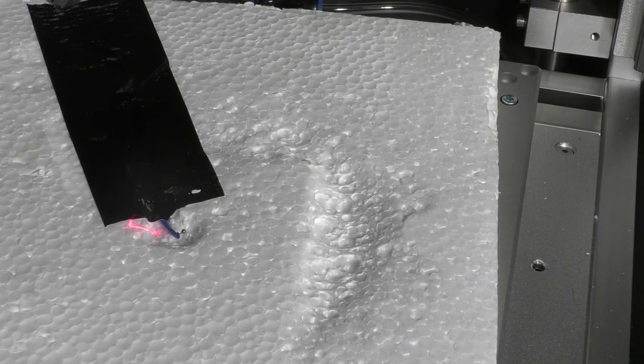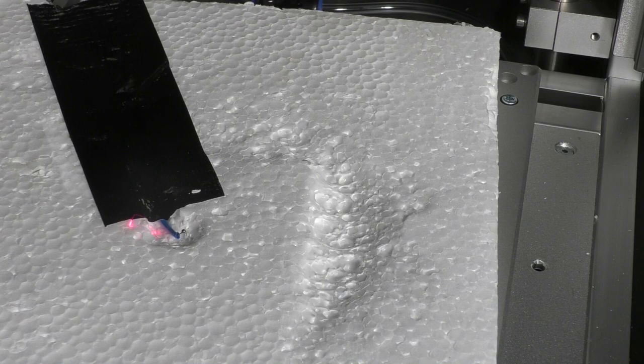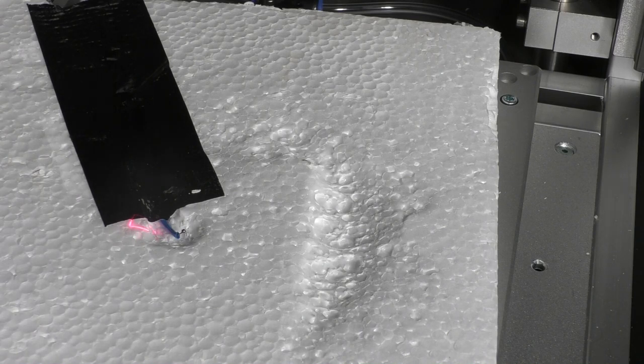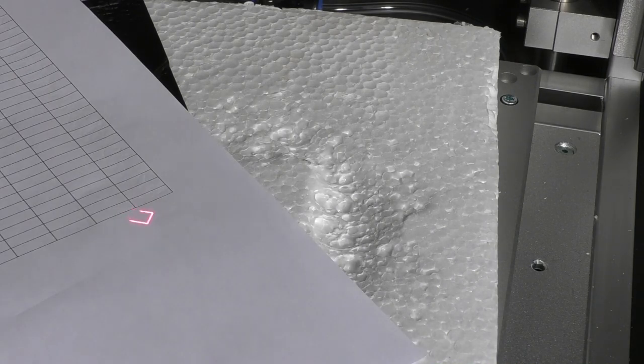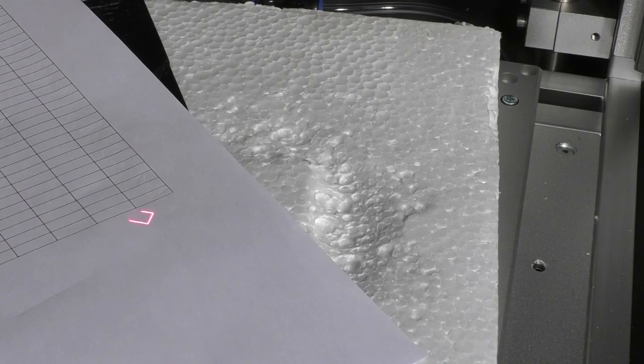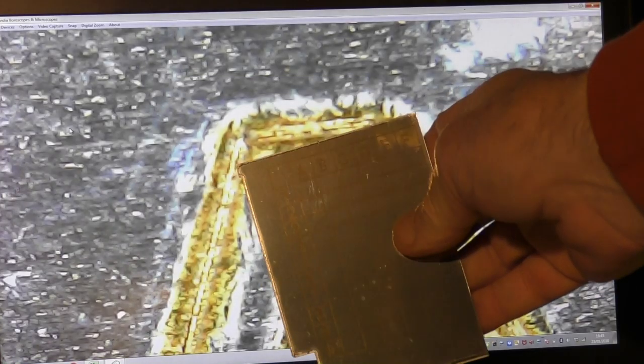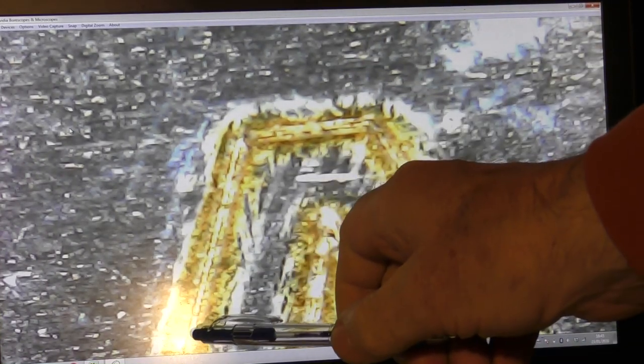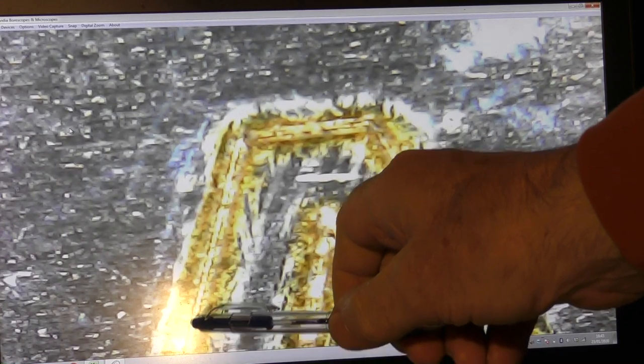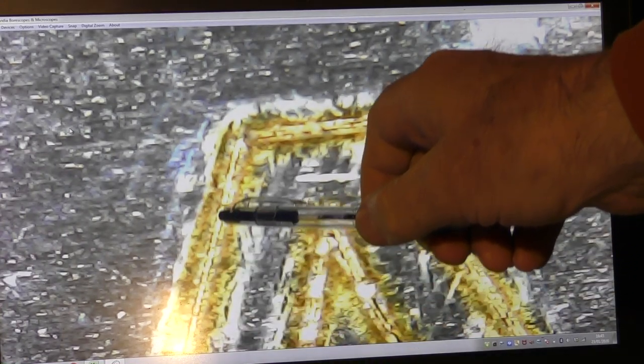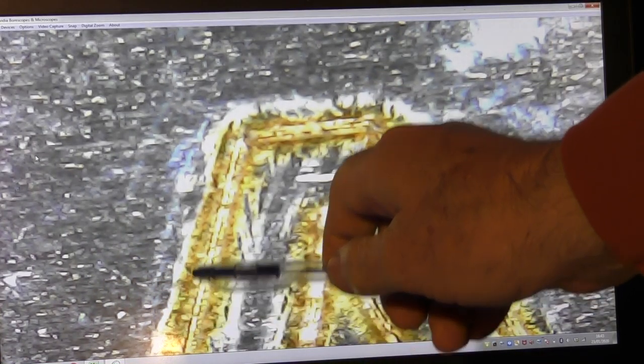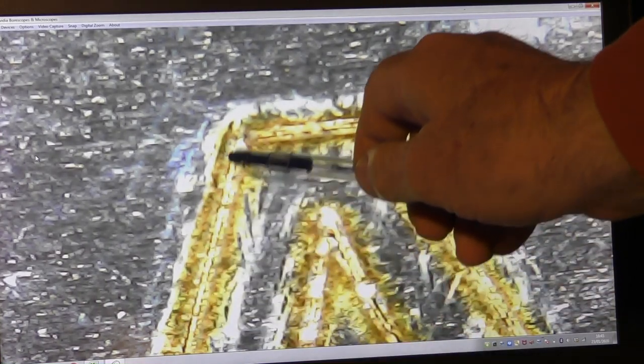So we need to go hunting in a different area. We found the golds and the browns and a hint of blue, but we haven't got any other colors. Not entirely true. If we take a look at on my grid pattern there, this is the top of the A that I've drawn in, and here we can clearly see what I was speaking about earlier. The thin line down the center where we've got maximum power at the center of the beam, and then around the edge here we've got the lower power which has given us the yellow or the goldy color, very distinct brown yellowy color. This is a six nanosecond pulse, 400 kilohertz, a 0.1 line spacing, so the line spacing is bigger than the spot size, and it was done at 460 millimeters a second.